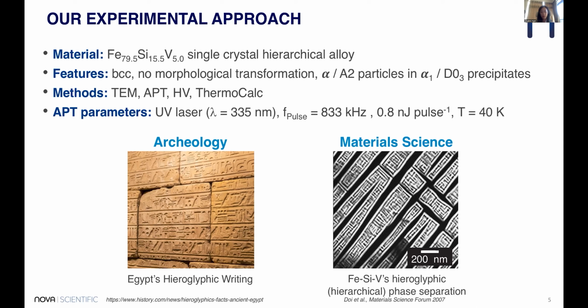Here we use TEM, atom probe, hardness measurement and thermal calculations. The atom probe experiments were done in a straight flight path LEAP 5000 XS equipped with a UV laser. We use a laser pulse frequency of 833 kilohertz, a laser pulse energy of 0.8 nanojoule, and the sample is kept at 40 Kelvin during analysis. Our alloy's microstructure looks a bit like Egyptian hieroglyphic writing. So let's take a look now at the iron silicon vanadium hieroglyphic hierarchical phase separation.